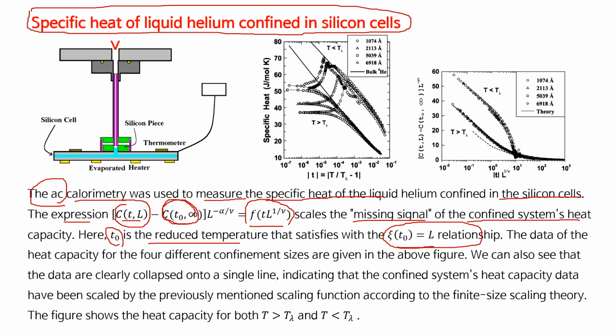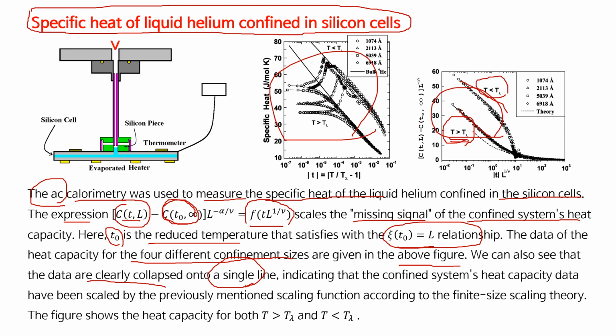The data of the heat capacity for the 4 different confinement sizes are given in the above figure. We can also see that the data are clearly collapsed onto a single line. This line you can see here, single line. T is larger than the critical temperature, and T less than the critical temperature for the bulk system. So you can see that the data are clearly collapsed onto a single line, indicating that the confined system's heat capacity data has been scaled by the previously mentioned scaling function according to the finite size scaling theory.